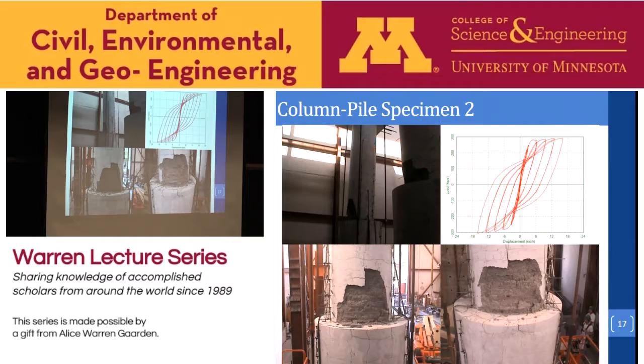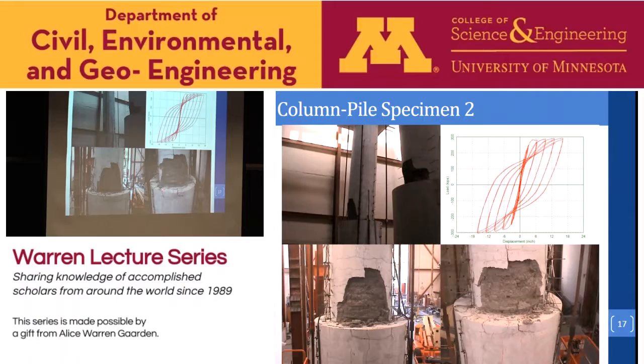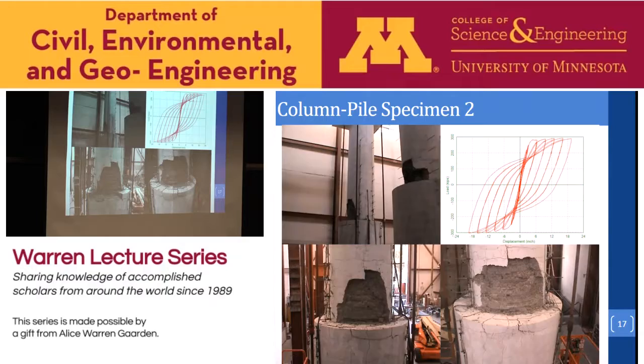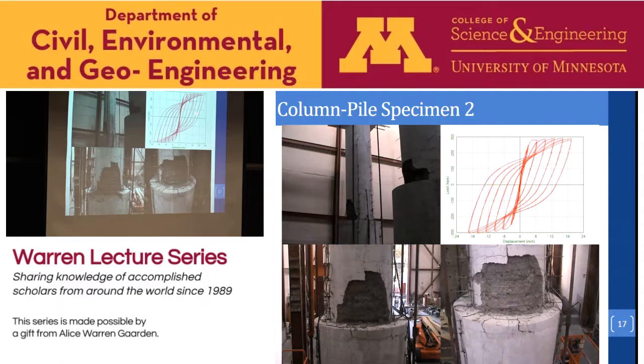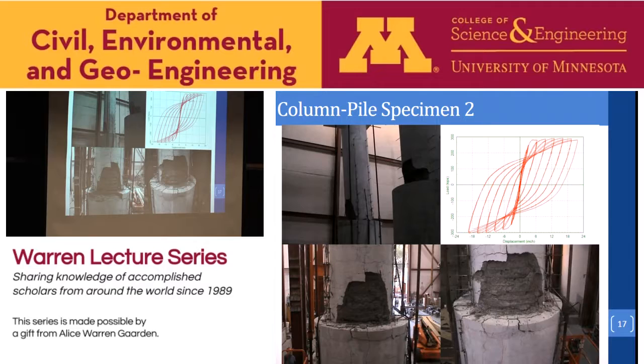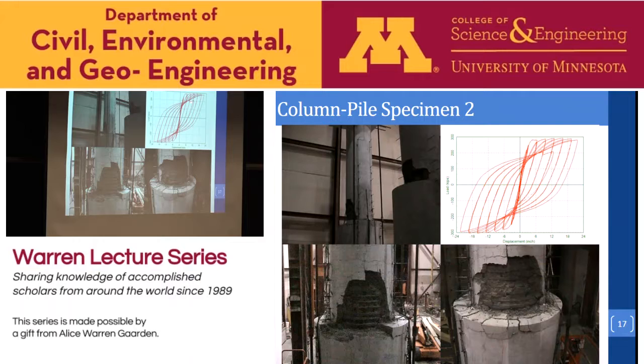And also, we see some cracking develop here, so a block of concrete started to pull out. A lot of damage occurred in this region. But the embedment length seems to be sufficient to develop the full tensile capacity of the reinforcement up to buckling and fracture. Actually, there were a number of bar fractures; you could see the drop of load here due to the rupture of the bars.